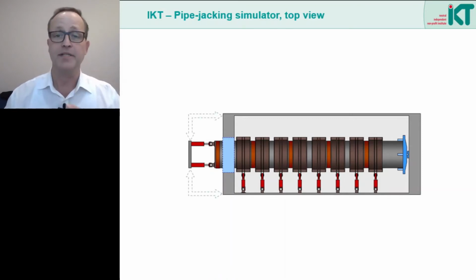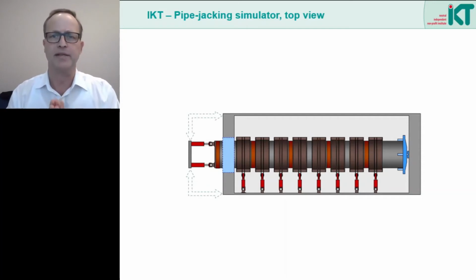The jacking abutment is connected externally to the test stand, so that the abutment forces can be transmitted into the test stand itself. But the most interesting element are the lateral forces. They are provided by 8 lateral pressure jacks. These jacks are connected to steel rings in which the pipes are held. Between the pipes and the steel rings, we placed special hydraulic cushions which ensure an even bedding of the pipe within the steel ring. And the rings themselves lie on Teflon plates so that they can be moved easily sideways.